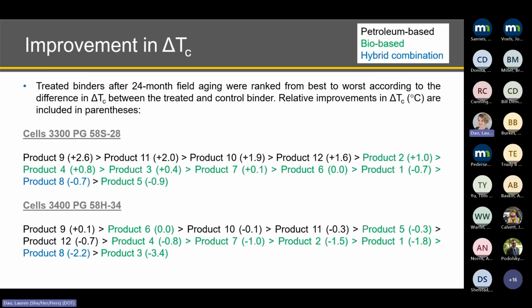So, trying to summarize what was presented in terms of the effects of the treatments in the delta TC of the binders, a ranking was established, just for us to try to see if what was captured can facilitate us when ranking categories of products and their effects on reducing the cracking potential of binders. So you can see here the difference between the delta TC of the treated sections and control sections after 24 months of being applied to the field.